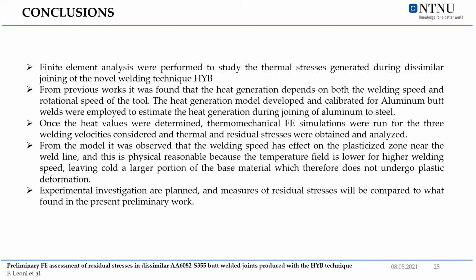Once the heat values were determined, thermomechanical finite element simulations were run for the 3 welding velocities, and the thermal and residual stresses were obtained and analyzed. From the model, it was observed that the welding speed has an effect on the plasticized zone near the weld line. And this is physically reasonable because the temperature field is lower for higher welding speed, leaving cold a larger portion of the base material, which therefore does not undergo plastic deformation.